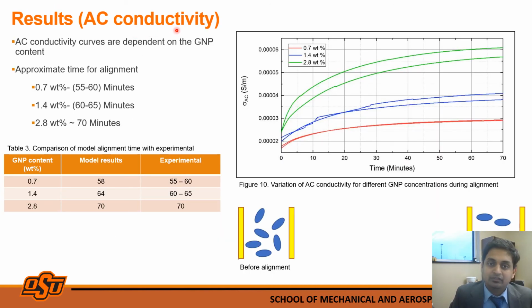Let's look at some of the experimental results. In figure 10, you can see the AC conductivity variation for three different weight fractions as the alignment process is taking place. Initially, at time t equal to 0, each sample has a limited amount of conductivity present, and as time passes by, they tend to get aligned and formation of chains takes place, as seen in this picture before alignment and after alignment, and the conductivity increases and it plateaus. The approximate time for alignment is figured out based on the amount of time it takes to plateau. Comparing it with model results, we get a reasonably good comparison, which also validates the model that viscosity is an important factor for alignment.